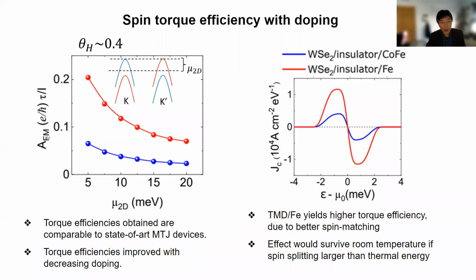But this number, 0.1, is also what you get for a spin transfer torque device based on MTJ. So we suggest that this configuration, even though it can be made more efficient by going to lower doping, and also by increasing the Hall angle closer to 1, the margin of improvement is not that impressive. Maybe you will get a few times an enhancement, but not an order of magnitude. But in any case, that is one of the first conclusions that we arrive at.